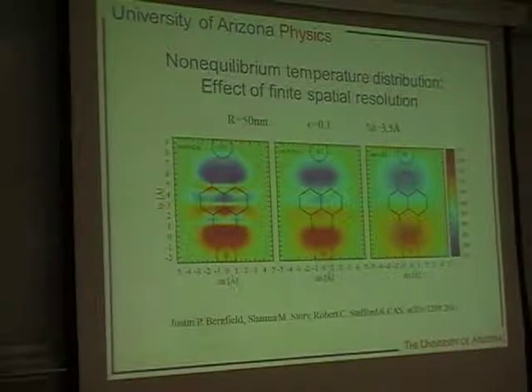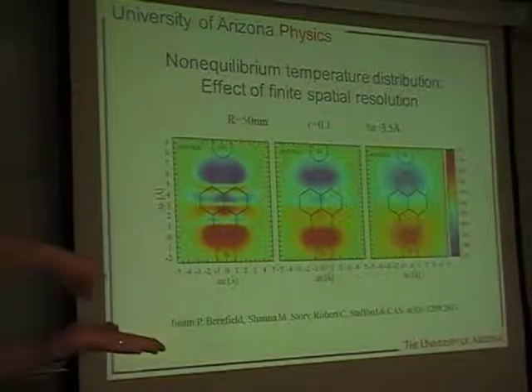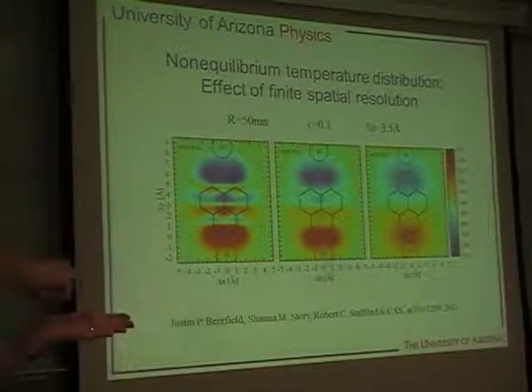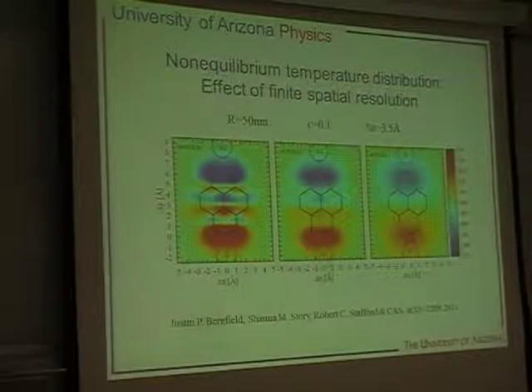And so here, I didn't go into enough detail about exactly how we modeled this thermometer. We model it as an atomically sharp platinum tip. In this case, it's held with the center of that platinum atom 3.5 angstroms above the plane of the molecule. Then we've done a microscopic calculation of the tunneling matrix elements between the tip and the molecule to calculate those transmission probabilities. So this is just the raw calculation with such an atomically sharp tip.